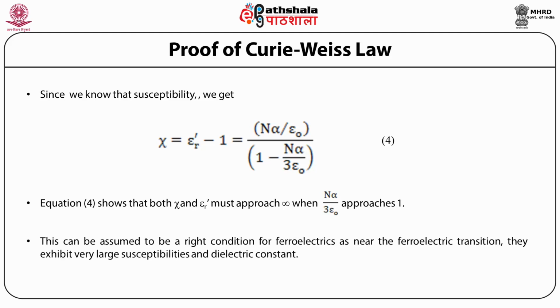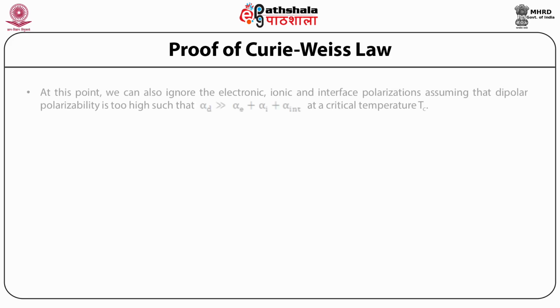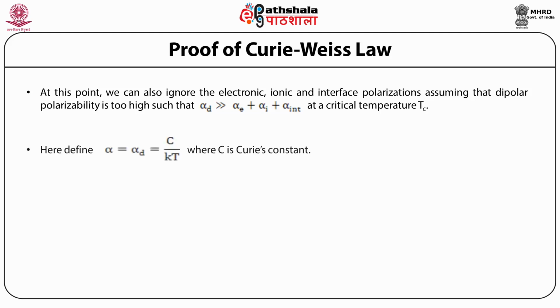This can be assumed to be the right condition for ferroelectrics, as near the ferroelectric transition they exhibit very large susceptibilities and dielectric constant. At this point, we can also ignore the electronic, ionic and interface polarizations, assuming that the dipolar polarizability is so high that alpha D is very much greater than alpha E plus alpha I plus alpha int at a critical temperature Tc. Here, alpha is alpha D, which is equal to C by kT, where C is the Curie constant.